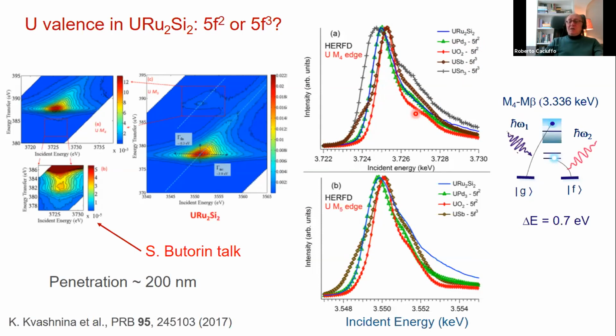Of course, it could be the case that the surface layers are oxidized, but in this case, the spectra should be similar to the one of UO2, which is an insulator. And you see that there is a shift of about 1 electron volt between the two cases. So the indication of these experiments is that they allow us to give a strong indication about the valence state of the compound.